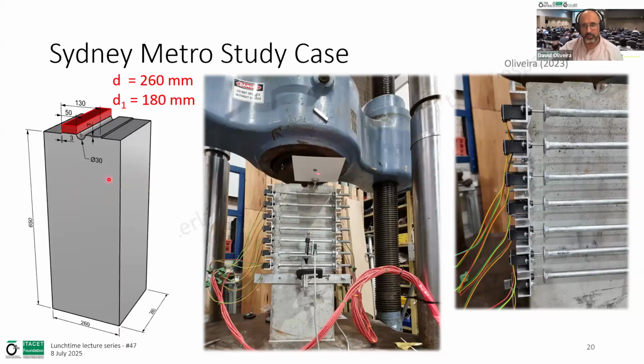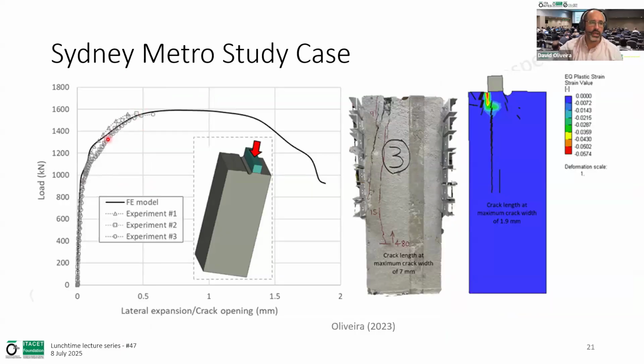these highly concentrated loads. And what we observed here is that for the 260 millimeters length, they achieved something in the order of 1.6 meganewtons. So this is not 1 meter. You will see later that once we multiply this by the 1 meter, we will get very close to what we were needing. Unfortunately, our compression machine wasn't displacement control, so it was only picking up to the peak load, and we were missing out on the post-peak behavior, which we picked up with our own numerical model to try to recalibrate the original predictions we had in design.